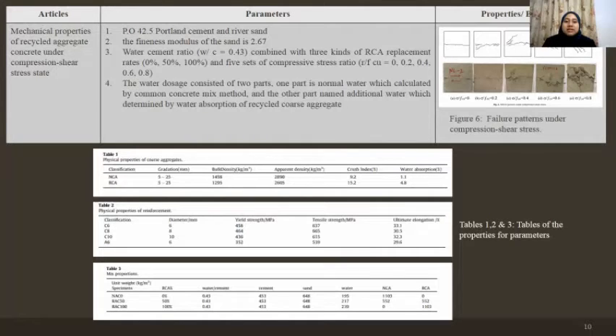The water dosage consists of 2 parts. One part is normal water, which is calculated by the common concrete mix method, and the other part is named additional water, which is determined by the water absorption of the recycled coarse aggregate. Figure 6 shows the properties or behavior that we can find in this article, which is failure patterns under the compression-shear stress.